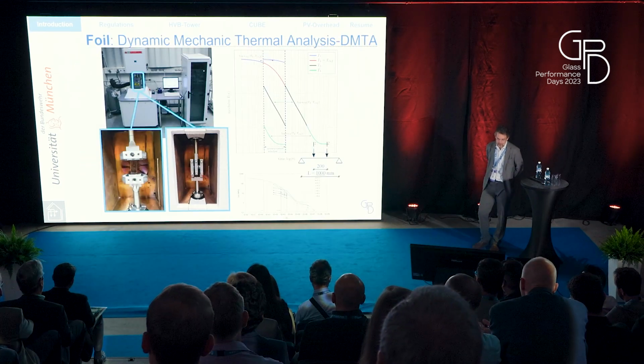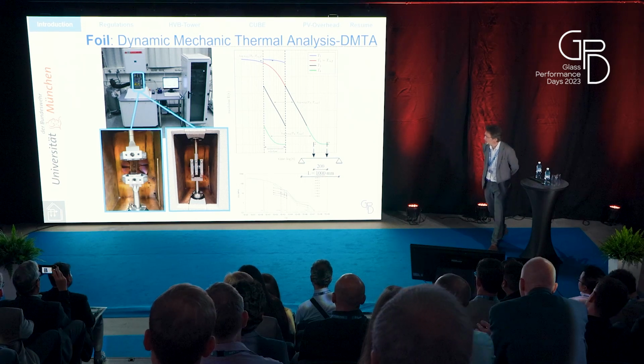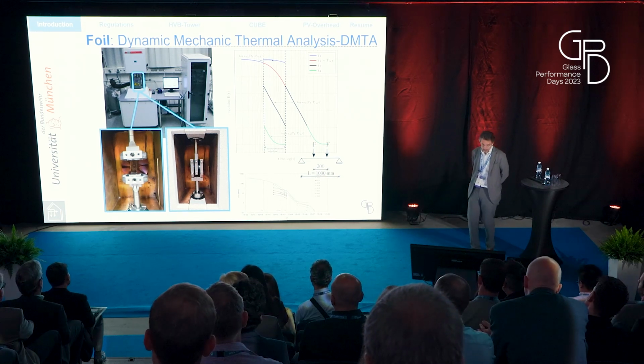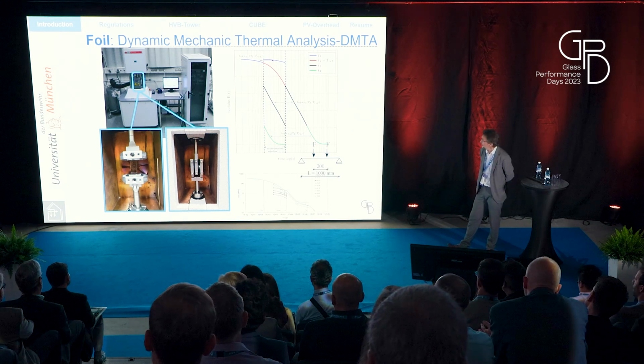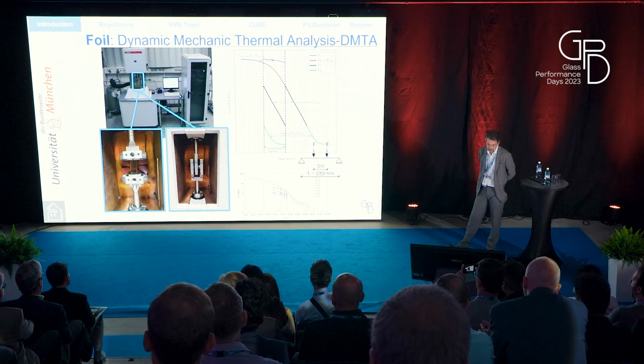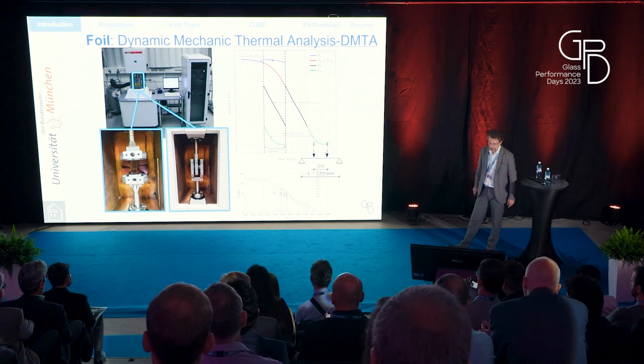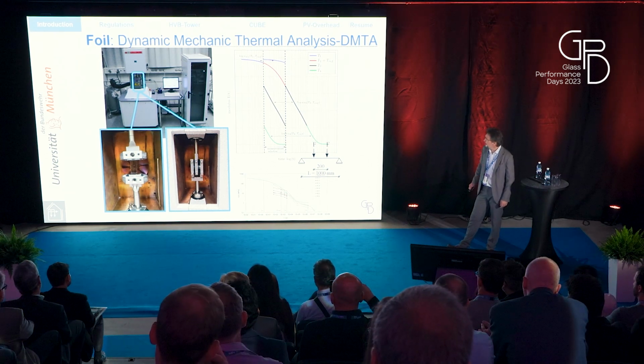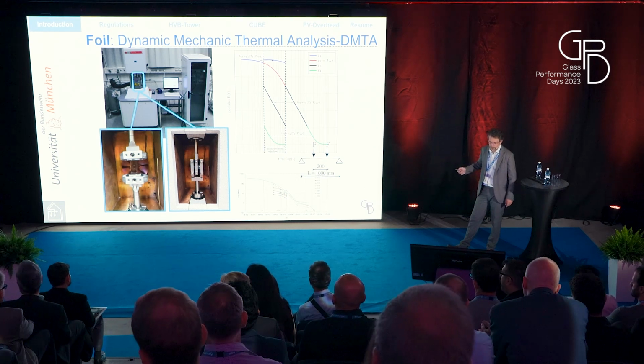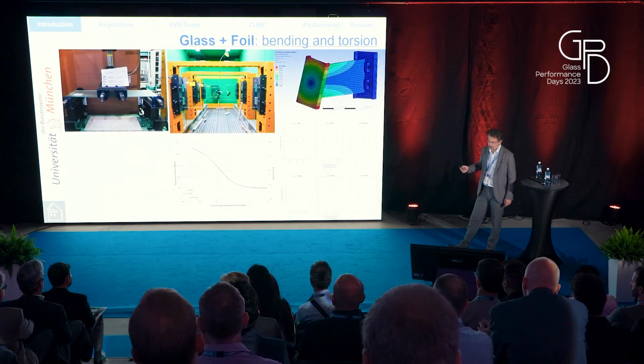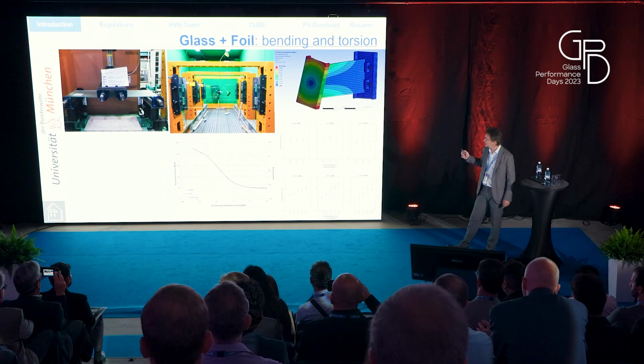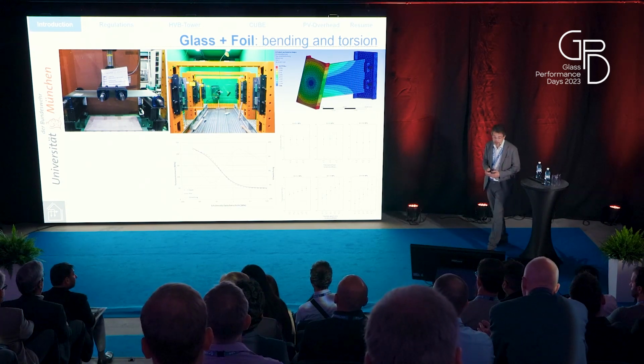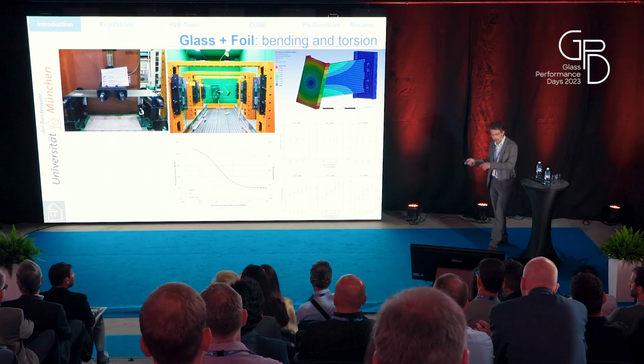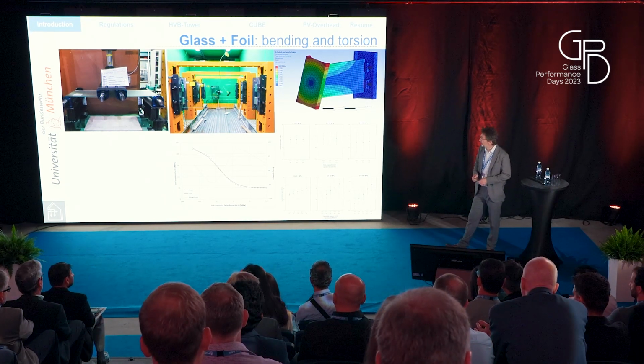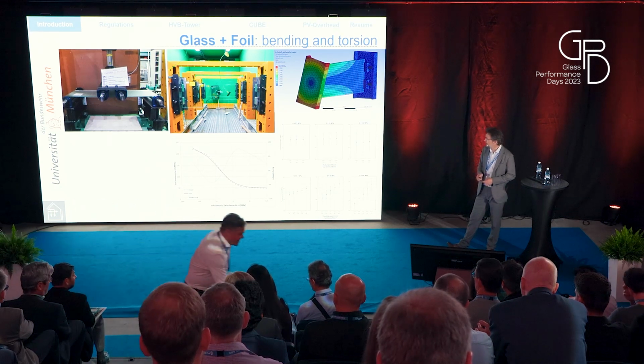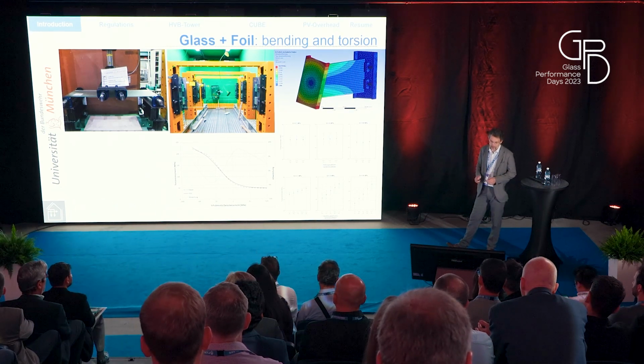A few words about material characterization. We do tests on the foil only by using, for example, the DMTA machine, having this highly sophisticated equipment, doing the time temperature shift, getting a master curve, and then we look at whether this behavior of the foil only matches with the laminated situation where we have glass plus foil. So we do bending tests, creeping tests, torsion tests, also under different temperature levels to see whether everything is matching.